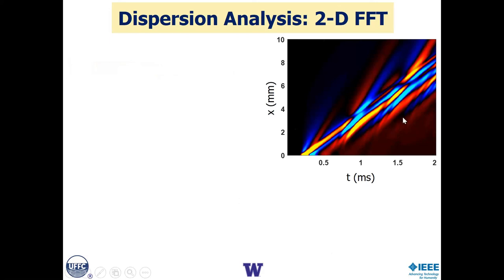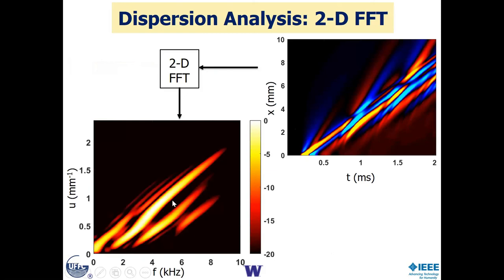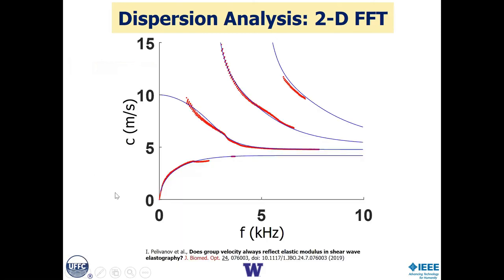However, we know from physical acoustics, from geophysics, from other areas of looking at mechanical wave propagation in layers, that we can do spectral analysis of these waveforms. And from that, get dispersion relations and their well-defined modes. And when we do that and plot them in a more characteristic format for dispersion analysis, where we're looking at the propagation wave speed as a function of frequency, we get these characteristic modes, the A0 mode, the S0, so the antisymmetric and symmetric modes, and higher order modes. If you can measure these, though, over a wide range of frequencies, as we can with our micro-tapping experiments, we can then fit to one of these modes, as we do here in an A0 mode, and from that estimate the high frequency asymptote, which is the bulk characteristic. So with dispersion analysis, we can get these bulk characteristics.